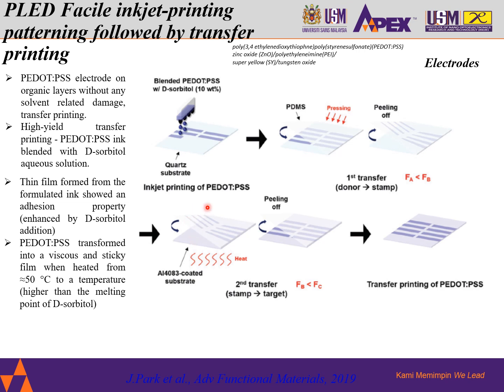So with that adhesion property, it shows that the solid form of PEDOT:PSS is transformed into a viscous and sticky film when heated around 50 degrees C. Then you can simply peel it off and do the transfer printing of the PEDOT:PSS that you fabricated.